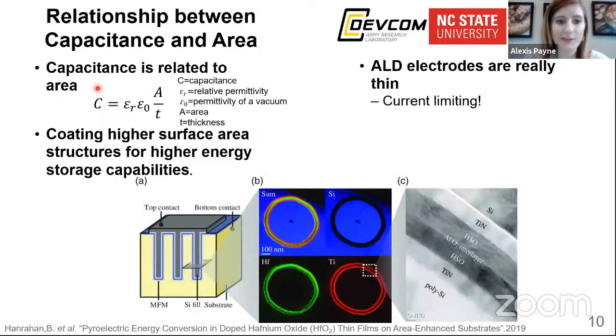Makes sense. So Ryan's asking, from the slide about the operating voltage, increasing the percentage of alumina in hafnia as well as the thickness seemed to keep improving performance. Is there a limit to this, or is there a Goldilocks scenario? So that's a great question, Ryan. And there is a limit. And the reason why is capacitance is related to area. And if I go back to that slide, you can see this equation. So as much as increasing your surface area increases your capacitance, as you increase your film thickness, you get a decrease in your capacitance. So there is some point where you grow so thick, you're being a detriment to yourself. And also at some point, your dopant won't form a homogeneous thin film, and that'll probably lead to not great electrical properties. So you don't want to keep increasing the dopant concentration indefinitely.